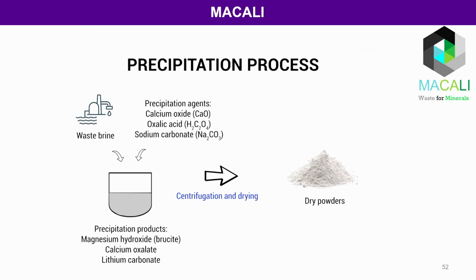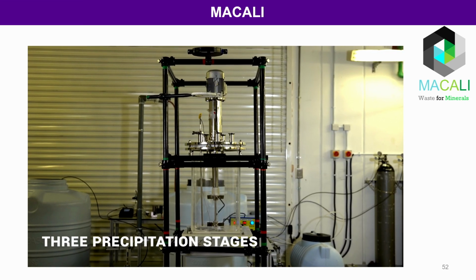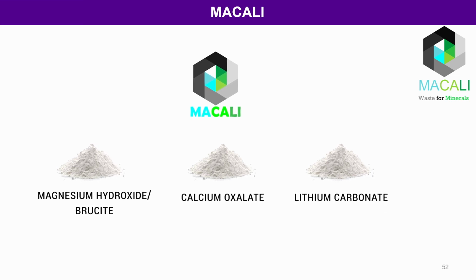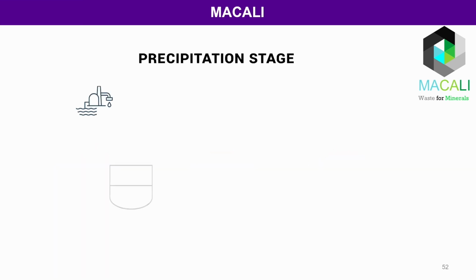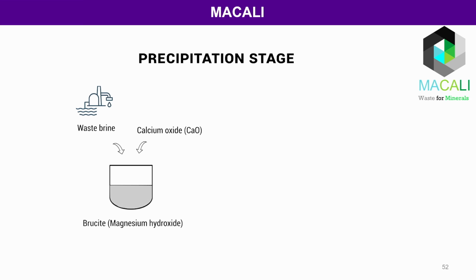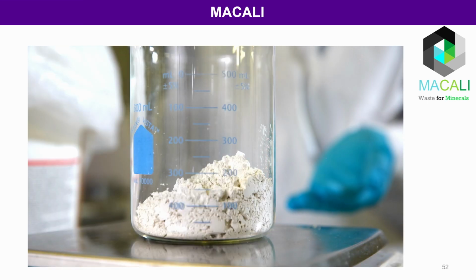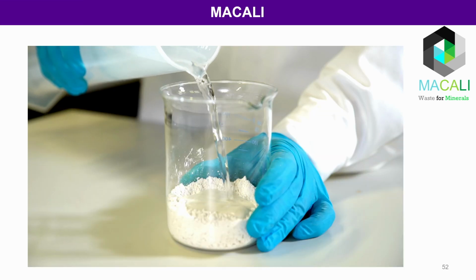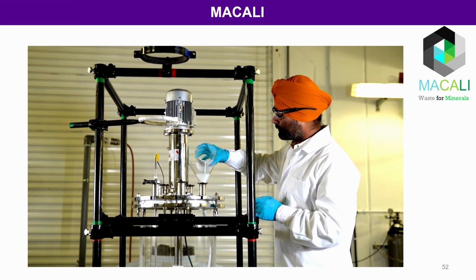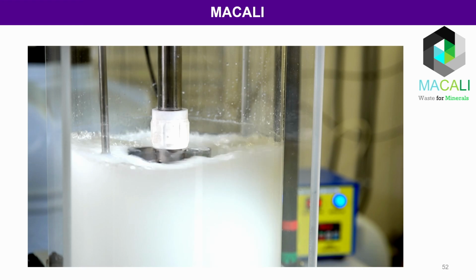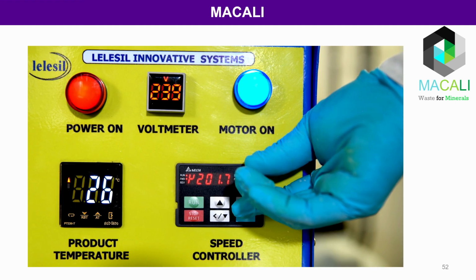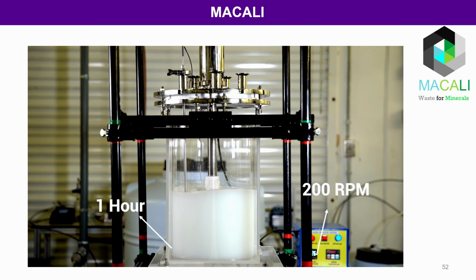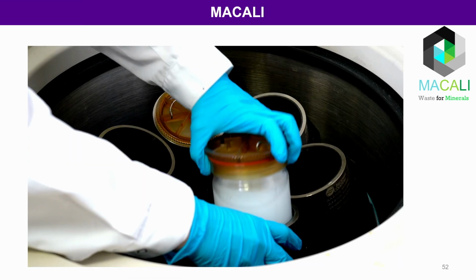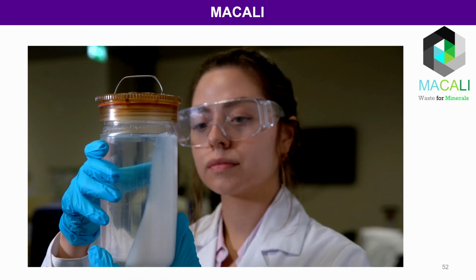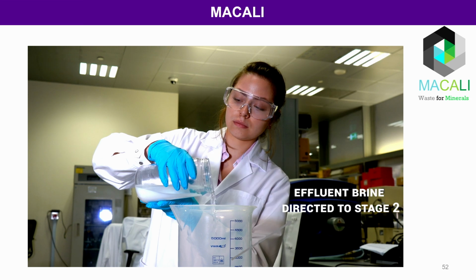This technology combines 3 stages involving chemical precipitation for the recovery of these minerals. In stage 1, we employ a simple precipitation process to synthesize brucite from reject brine. In the synthetic procedure, calcium oxide, a cost-efficient precipitation agent, is mixed with deionized water, which is then added to 15 liters of brine. The solution is stirred for 1 hour. The milky solution is then centrifuged to separate the powders and calcium-rich brine, directed to stage 2.